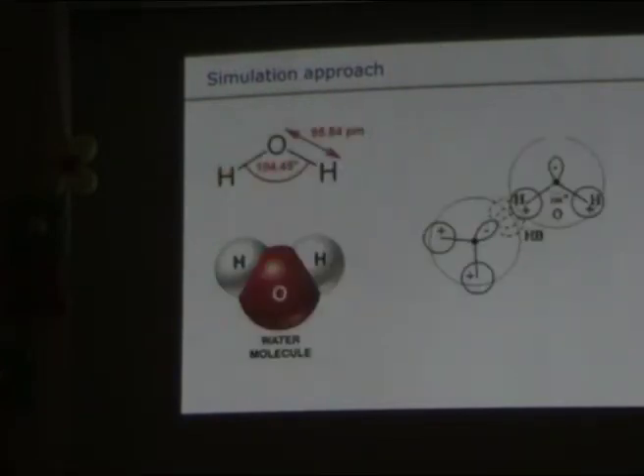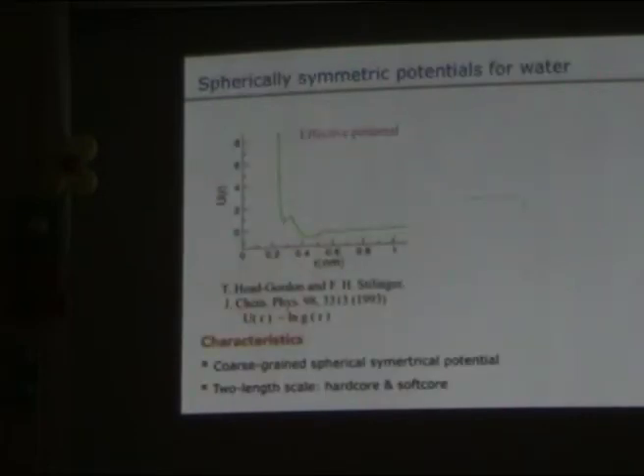We listed several materials at the very beginning of the presentation. It's not only water; there is a group of materials that show indications of a liquid transition. So we try to take out as much information about water as possible, and we just use a coarse-grained model. For instance, for water, we know that it's one oxygen and two hydrogens with some angle between them. Instead of using this molecular structure, we use coarse-grained particles to take the place of the water molecule. So we have one sphere, another sphere, and they interact with each other through potentials that we are showing right here. For instance, if you measure the structure information from liquid water, here's what you get.